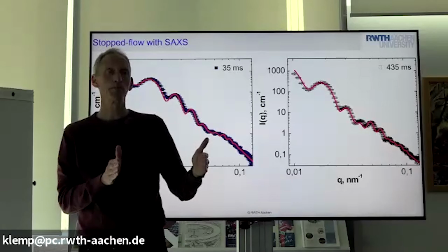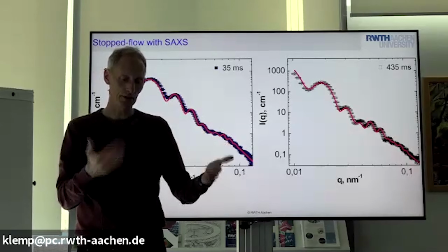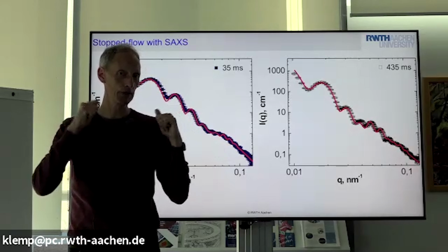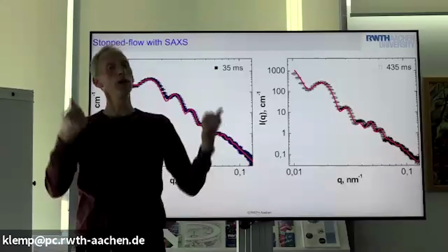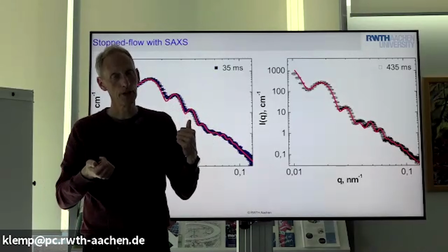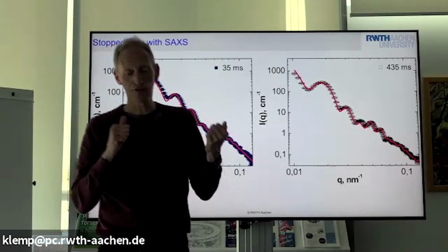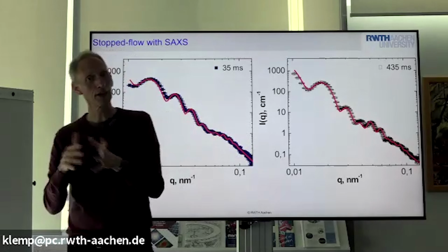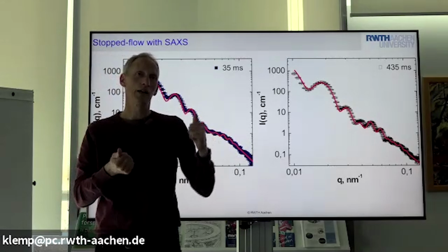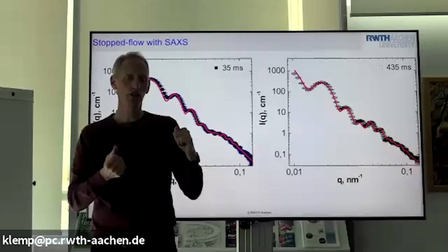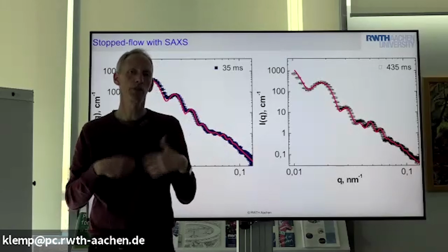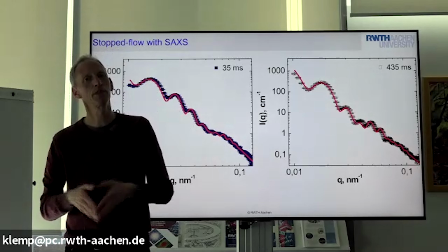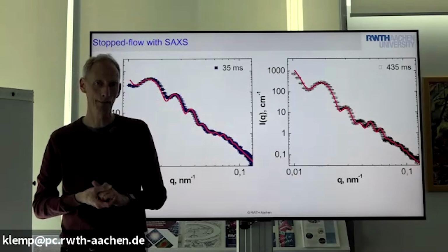Now, when we purify the whole system, these few charges sitting at the surface during the polymerization are sufficient to stabilize them. Now, when we add salt, they flocculate. And if we, for instance, add a surfactant during the polymerization to make them small, and then remove the surfactant afterwards, then these systems are less stable at high temperature, and very small amounts of salt affect this, and then they flocculate. So it's basically a charge stabilization in the collapsed state that makes them stable.